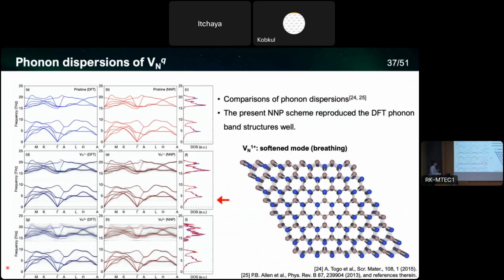Then we verify the performance of our neural network potential by getting the phonon dispersion with the presence of nitrogen vacancy with different charge states. The upper panel shows the pristine phonon dispersions. The left one is obtained by density functional theory, and the graph in the middle is the result of the neural network potential. The comparisons are quite good. These unfolded phonon dispersions are quite difficult to differentiate, but if you look at the density of states, you can see that the differences are quite minor. And in the +3 charge state, there are some deviations, but overall predictions are quite good.